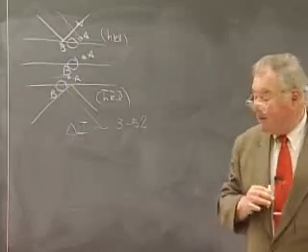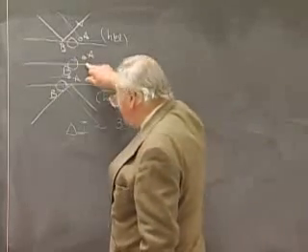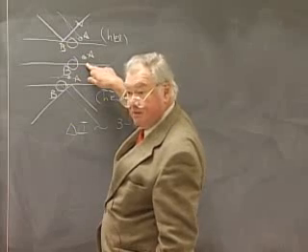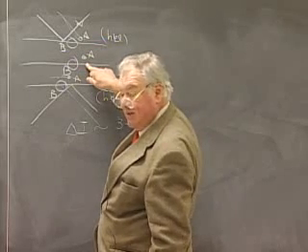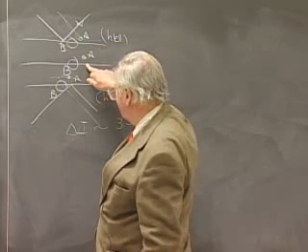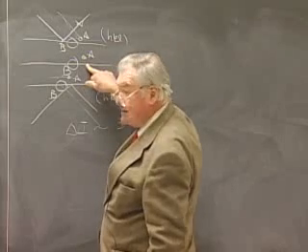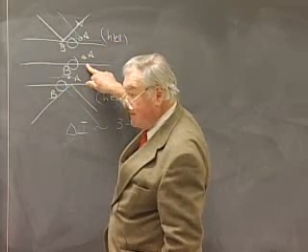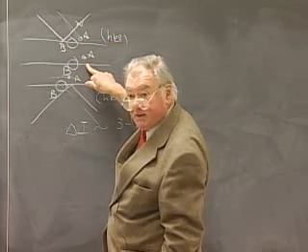Okay, so you can, with this careful measurement of intensity, distinguish between the opposite sides of a given set of Bragg planes, unless, of course, the crystal did have inversion in it, and then there would be no difference at all. It requires a very careful experiment, though, because there are many things that could make the intensities different. For example, absorption by the crystal.